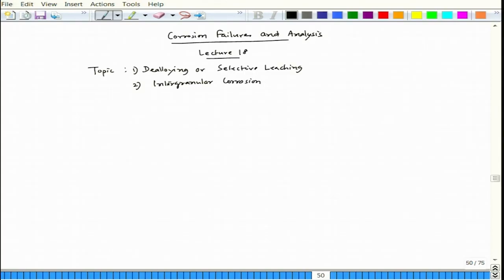If you recall our previous lecture, lecture 17, we started talking about some examples. In the case of the silver-zinc system, we could get a pure silver network starting from a very lean silver-containing alloy composition — silver 25, zinc 75. Similarly, we saw formation of zinc oxide nano rods on top of a nickel core by doing dealloying of a nickel-zinc alloy.